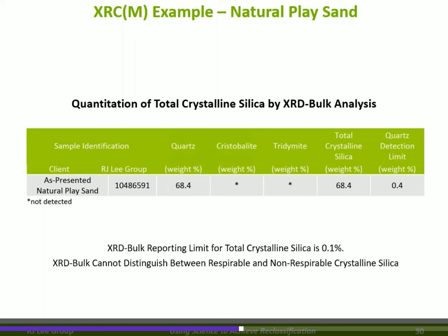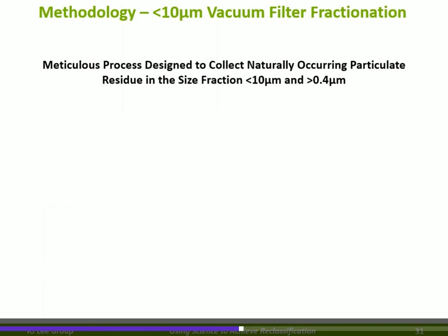A couple of notes. The XRD bulk reporting limit for total crystalline silica is 0.1%. That becomes important. XRD bulk cannot distinguish between respirable and non-respirable crystalline silica. It doesn't even try. So, we're not there yet. We need to fractionate that material very carefully so that we can get that fraction between 0.4, which is our lower threshold, and 10, which is our upper threshold. And we need to do it in such a manner that that respirable particulate is not affected by the process.